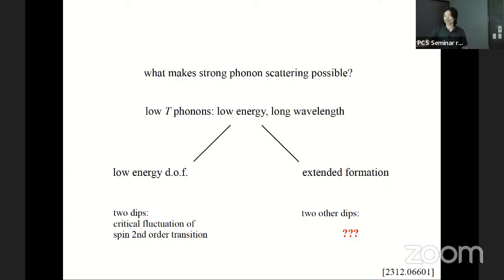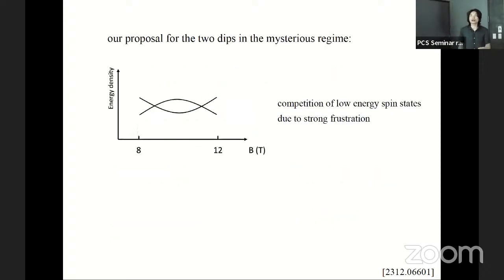It's more non-trivial. So we propose this is related to extended deformation. We also tried some other low energy degrees of freedom and we excluded them. Well, I'm not going to explain how. But we tried the explanation of extended deformation. That is scattering with the long wavelength phonon. But what extended deformation? It turns out that we propose a very simple mechanism. That is the simplest mechanism we can think of that is compatible with all the experiments so far.